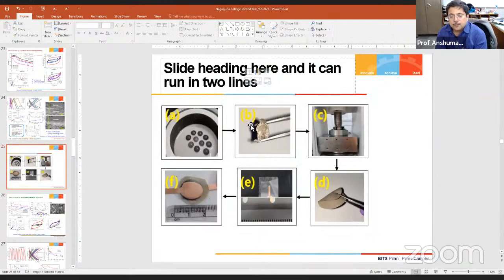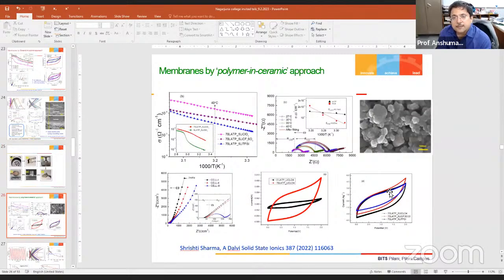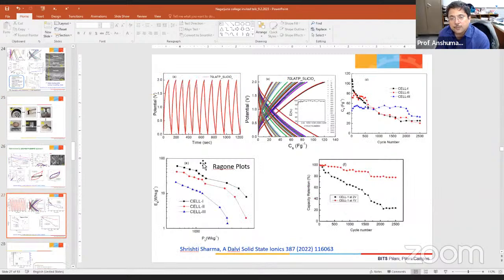Here we have used some ball milling also, because ball milling is required to mix the ceramic particles with polymer very properly. If you just do it in a pestle mortar or with a magnetic stirrer, it will not work. You have to use a proper ball mill, and using a ball mill gives very good results. And these are the ceramic films actually. These are the predominant ceramic sheets where a little amount of polymer is added. All right. So with the polymer and ceramic approach also, we have shown that it shows a very interesting result.